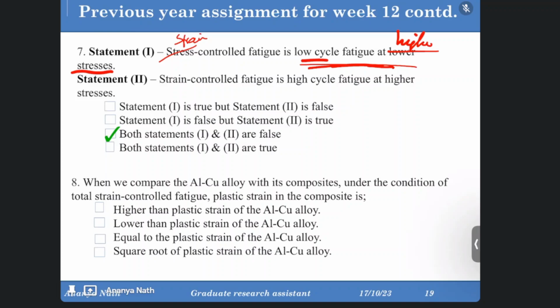When we compare the aluminum copper alloy with its composites under the condition of total strain control fatigue, the plastic strain in the composite is higher than the plastic strain of the alloy. So that means the fatigue life is decreased in the case of composites because the strain is more here. So it will have lower time to fail than the alloy.